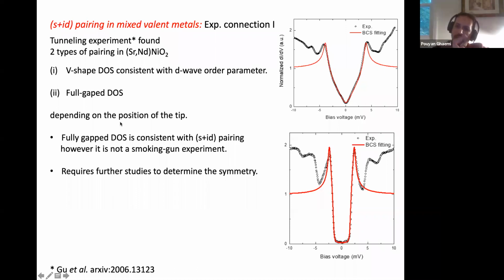Oh, no, but this is spatially resolved. A different position on the sample gives you different results, yes. And this suggests that they are close in energy, that in certain places there are patches of different type. Experiment says that there are patches of D-wave coexisting with fully gapped superconductivity. That's what experiment says, and it's not clear what this is. And if they're close in energy, you expect this one to be D plus something. You don't expect a completely different channel to overpower. But again, it requires further experiments to see.